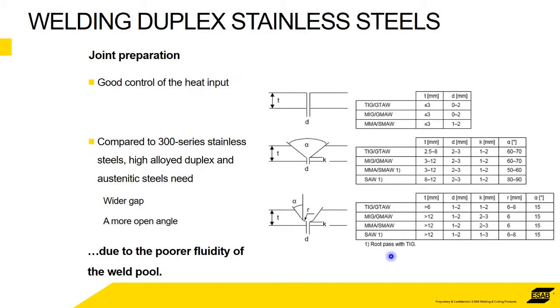Exactly what we talk about with all kinds of welding. Okay, joint preparation: with the higher alloys, to put it in layman's terms, the weld pool becomes stickier, more like chewing gum. So in order to compensate for that, you need to design the joint to be wider. The joint gaps need to be wider to enable the poor fluidity of the weld pool to flow into the joints. Okay, if you don't, then you're going to get lack of fusion areas.